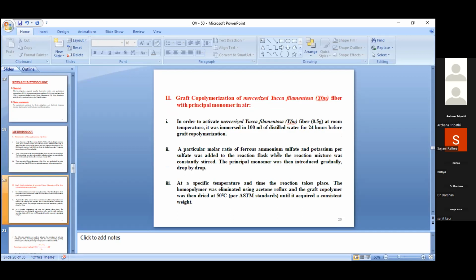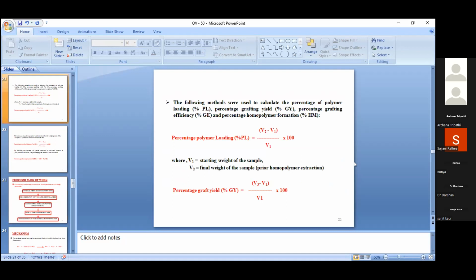Graft copolymerization of mercerized yucca filamentosa fiber with principal monomer in air. In order to activate the mercerized yucca filamentosa fiber at room temperature, it was immersed in 100 ml of distilled water for 24 hours before graft copolymerization. A particular molar ratio of ferrous ammonium sulfate and potassium persulfate initiator was added to the reaction flask, while the reaction mixture was constantly stirred. The principal monomer was then introduced gradually drop by drop. At a specific temperature and time, the reaction takes place. The homopolymer was eliminated using acetone reflux, and the graft copolymer was then dried at 50 degrees Celsius as per ASTM standard until it acquired a consistent weight. The following methods were used to calculate the percentage of polymer loading, percentage grafting yield, percentage graft efficiency, and percentage homopolymer formation.